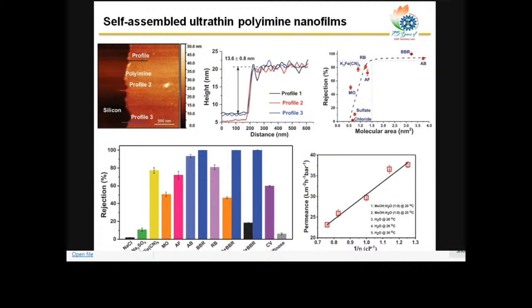Similar to the previous case, as I said, the permeance is dependent on the viscosity only here, because the pore size is bigger and the solvent molecules do not have much interaction. So it does not depend on the polarity or other molecular size. It simply depends on the viscosity. So the inverse of viscosity and permeance is linear here.